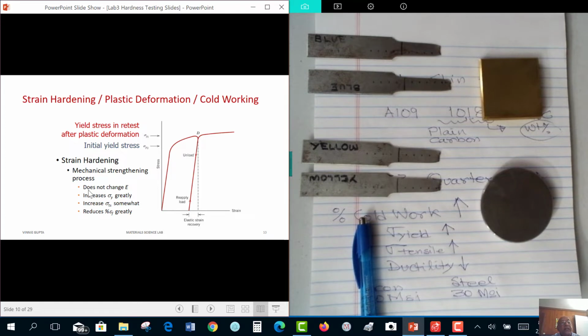And as we just noticed, in this mechanical strengthening process, we do not change elastic modulus. We do increase, depending on the material, yield strength greatly. We increase the tensile strength somewhat, and we reduce ductility greatly. You are going to learn, hopefully in a few weeks, that during this plastic deformation process, dislocations move and multiply. The dislocation density, if we go from, say, yield strength to tensile strength, increases by a factor of 100 to 1,000.